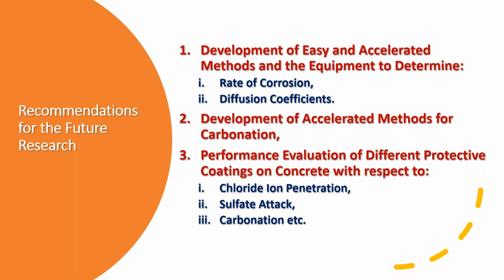So with chloride penetration, sulfate attack and carbonation, is it necessary to design the concrete with a higher grade of concrete, unnecessarily wasting? When we expect chloride penetration, sulfate attack and carbonation, instead of designing a concrete with a higher grade of concrete, after the completion of the structure we can use a protective coating. So that means we have to evaluate these protective coatings from time to time, and also the compatibility with the concretes. Then we'll be having a lot of savings. So this is one point I want to address to this august gathering.